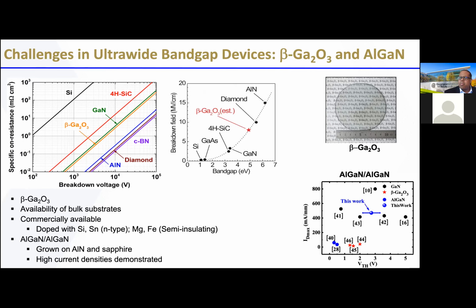And so the interesting thing, as I said before, is that we look at the specific on-state resistance for power. As you start moving up your band gap, we saw that there's this benefit. So I won't go over this again because we already talked about it. But the beta gallium oxide, what's nice is that it's grown from the melt, so you can get fairly good large area substrates for beta gallium oxide. Not necessarily cheap yet, but it's readily available.